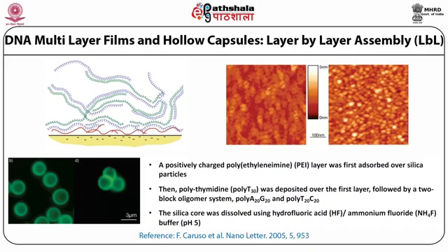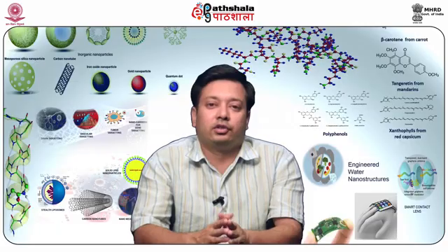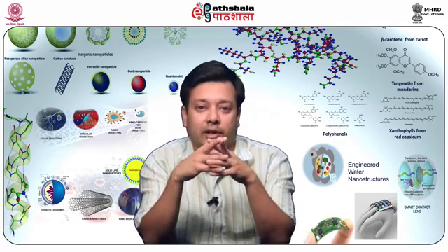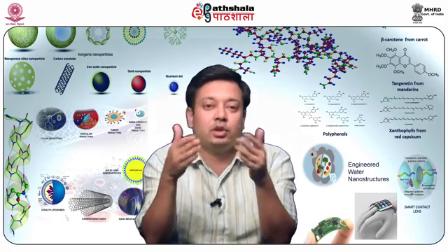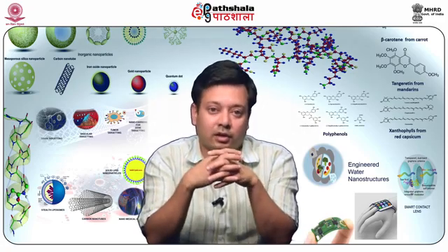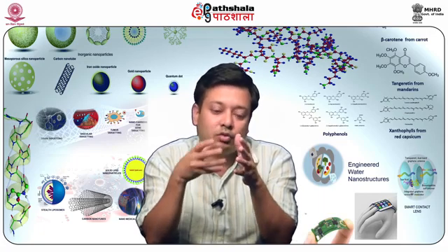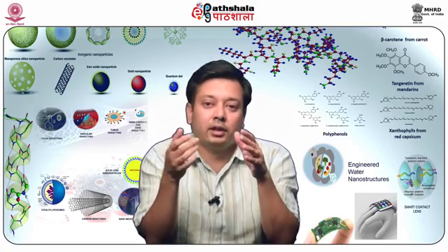Now when you put this kind of layer by layer self assembly on a silica particle, and then you dissolve the silica particle using hydrofluoric acid or ammonium hydrofluoric acid and fluoride, then you can actually create a hollow capsule which can be used as a nano container. So these inorganic nanostructures like gold nanoparticle, silver nanoparticle, or mesoporous silica nanoparticle can all be used for drug delivery application. Gold nanoparticle, as I said, can be used for drug delivery and sensing application,